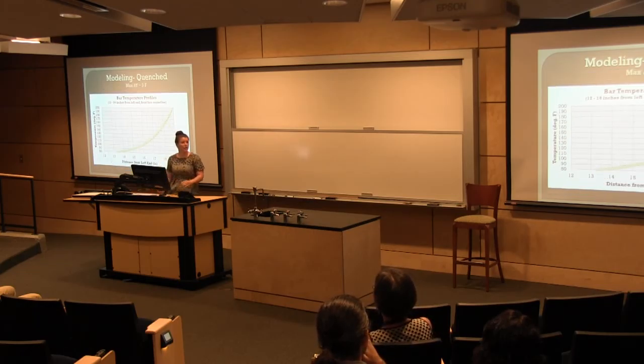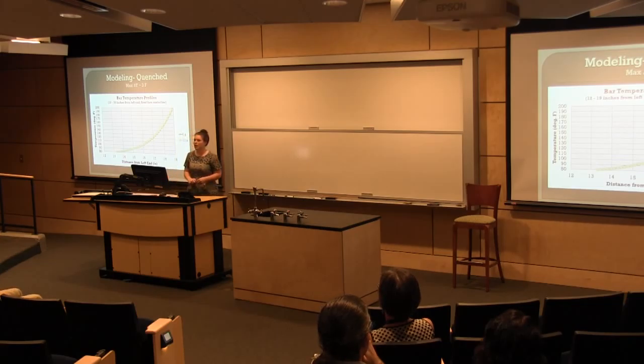Now, this is actually a blow-up of the same image, which kind of highlights what we're looking at here. And as you'll see, there's a max delta T of about 3 degrees with this, so that's what we took to be our first model of expected temperature rise with our conditions.